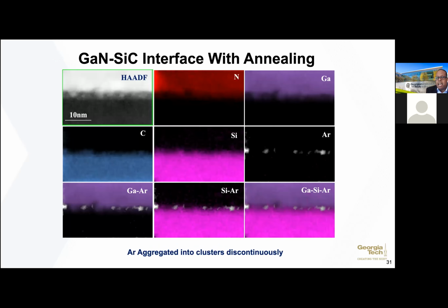The other aspect is that if you do TEM imaging plus chemical mapping, what we found is that you end up getting argon atoms that are trapped at this interface. And so this is sort of discontinuous after the annealing. If you don't do the anneal, it's actually a continuous layer of argon that's trapped here at the interface.